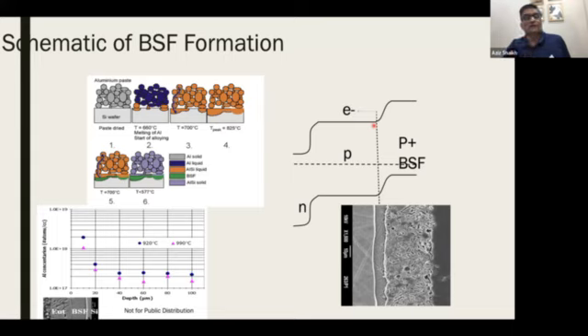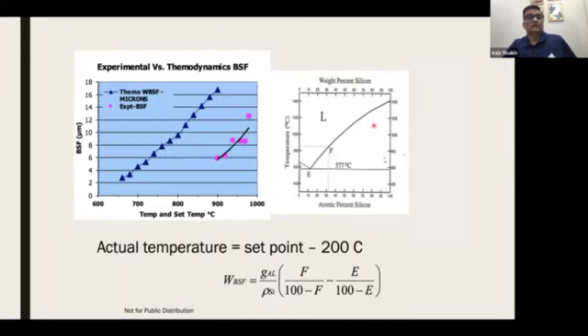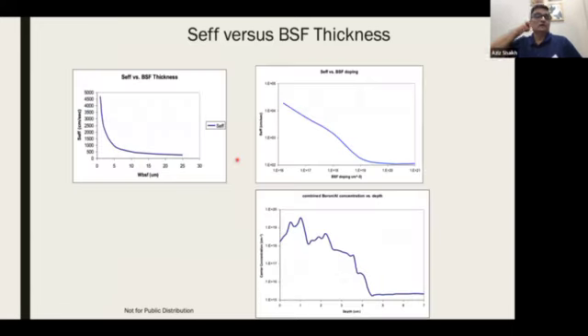Now, this was meant for students where I had to show them how the microstructure develops, so I'm going to skip this. And this actually shows that indeed, this is how it is, because there is a simulation where you can calculate the thickness of the back surface field. This is thermodynamically calculated, and this is the actual thickness, and they are off by about 200 degrees. The reason for that is thermodynamics looks at the equilibrium, but when we are firing it, it is a non-equilibrium system. Okay, so again, Abhay, I don't know whether this would answer your question, but what the back surface field does?